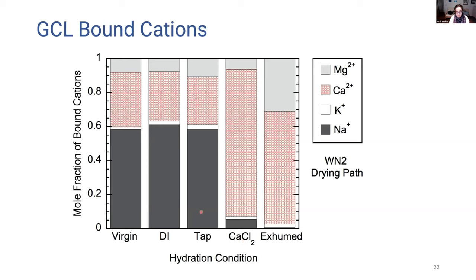For all these three cases, with the presence of high amounts of sodium, we expect to see both crystalline as well as osmotic swelling in the system. Over here, we basically have only crystalline swelling, not much osmotic swelling. And we observe this in the bulk GCL void ratio response also. We saw that for these materials, we had high bulk void ratios, a lot of swelling, a lot of hydration in the system, and not much swelling, not much change in moisture content with suction for these last two materials.